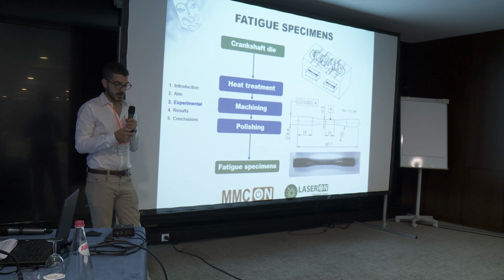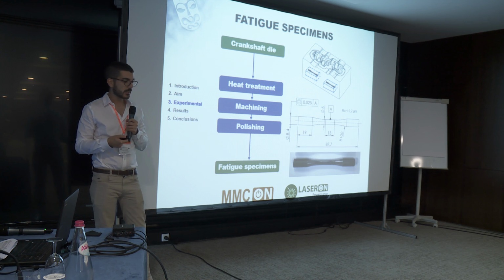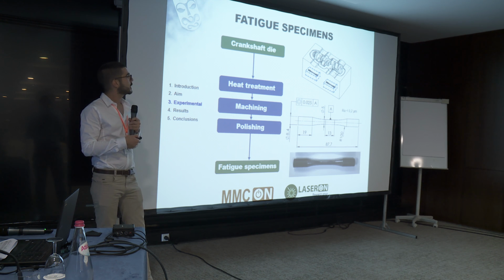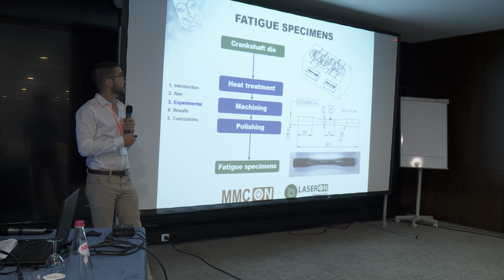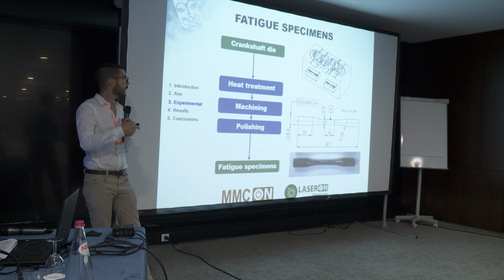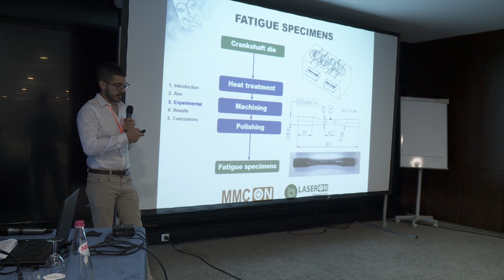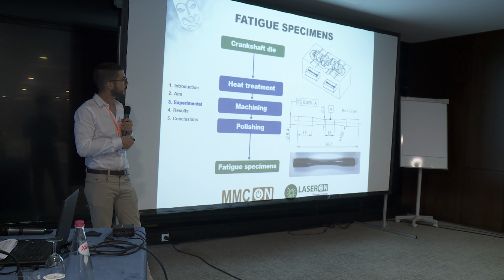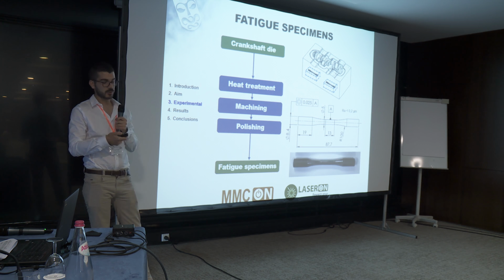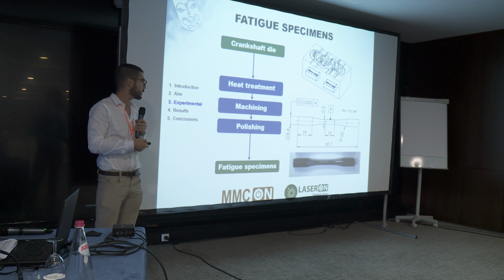So the fatigue specimens that we used for fatigue testing were extracted from an actual crankshaft die tool. Well, first we applied the heat treatment described on the previous slide to the crankshaft die. Then we extracted fatigue specimens from the block. We machined them according to these dimensions, and we polished them in order to avoid surface roughness effects on the results.